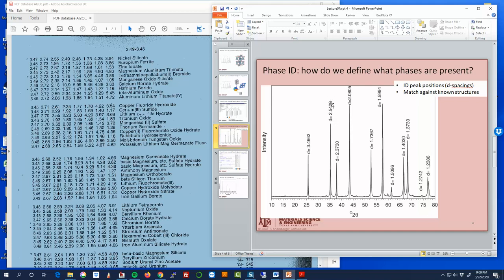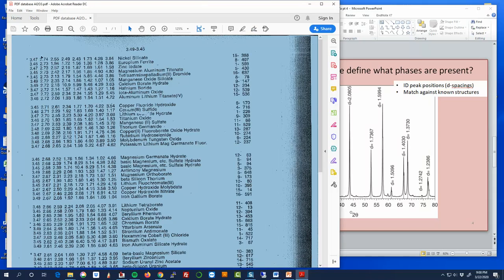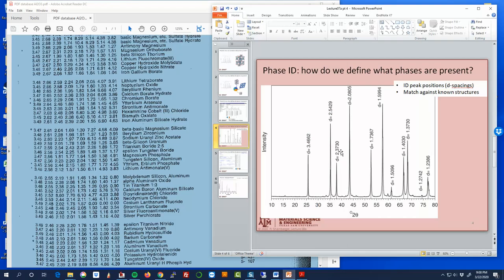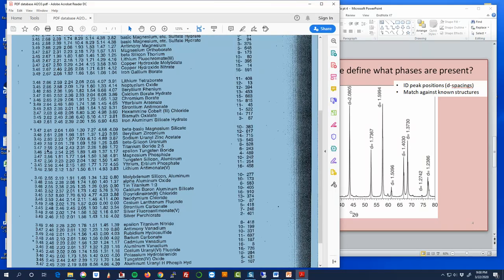Let's scroll down the list and see phases where the second peak is about 2.54 or 2.55. If I look at this second column, these are all too large, 2.73, getting smaller, getting smaller, and somewhere down here, 2.56, 2.55, down to 2.50. I think our phase hopefully is somewhere in this range. The next peak is at 2.37 and then 2.08. Those are kind of too far off.